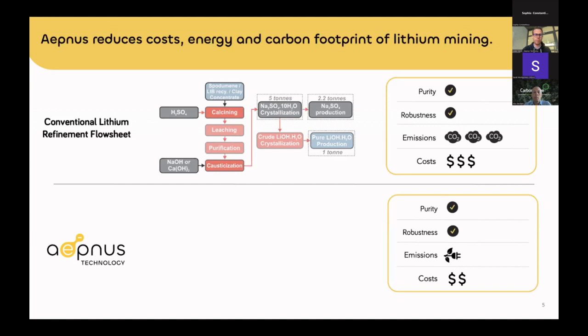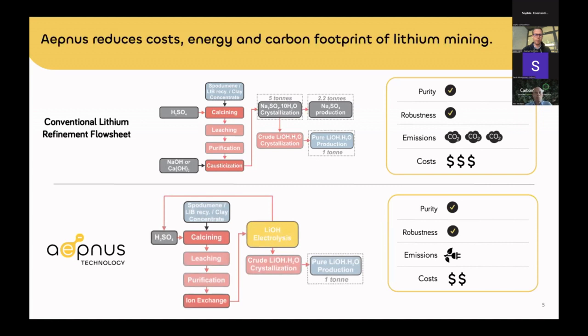This flow sheet, as it's employed by mining companies in Australia and also Canada, produces about 5 tons of CO2 emissions per ton of lithium hydroxide that's produced. And here is what the flow sheet looks like if Aepnus' electrolysis process was to be used instead. We can take in the lithium sulfate stream directly and, through the addition of electricity to our system, split water molecules to make hydroxide ions in situ, making lithium hydroxide in one step and recovering the sulfuric acid that's needed for the leach process in the very beginning.